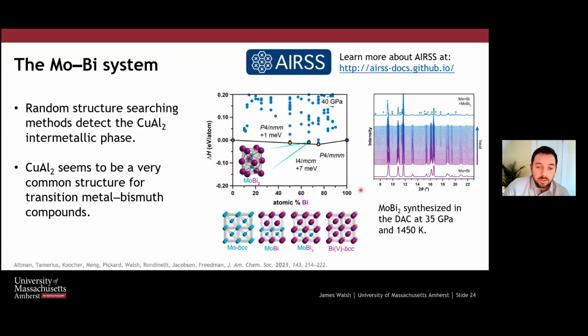Early on, we did collaborate with the Wolverton group at Northwestern. Max gave a really nice talk last September about his approaches. This is kind of the same approach. There are obviously differences in all of the crystal structure prediction packages, but we're ultimately using enthalpy calculated through DFT to predict whether a certain compound will be stable. And this is something that we were able to do in our group in-house.